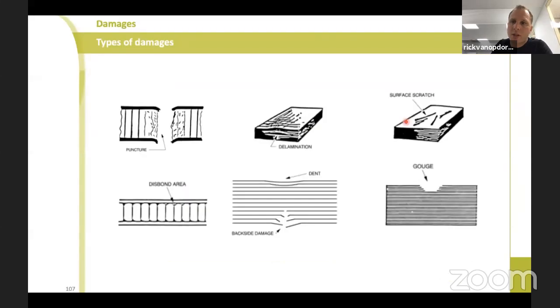Now, coming to damages, there are different types of damages that can occur in a composite. You have delamination, and the delamination is a damage between the layers, and that you normally can see with an inspection. And a disbond is between the honeycomb and the first layer of your composite. So that's the difference between a delamination and a disbond: this is with the honeycomb, first layer between honeycomb and the fiber, and this is between the fibers. Now we have a dent, a gouge, scratches to the surface.